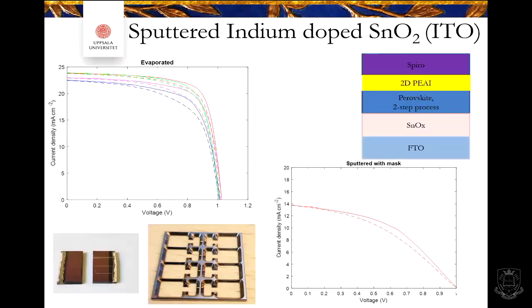Further on, we are still a little bit into the larger scale ideas to get larger solar cells. So here, what I wanted to investigate is sputtered indium doped tin oxide. It can already be used as an electron conductive layer, but could it also be used as a conductive layer in between later on in the solar cell? But right now, what you see here is a classical NIP junction. So here we have the electron conductive layer, perovskite, still a perovskite 2D layer to avoid humidity, which increases the efficiency a little bit, and then we have our spiro, and then we want to put our sputtered indium tin oxide on that. That was the first test.